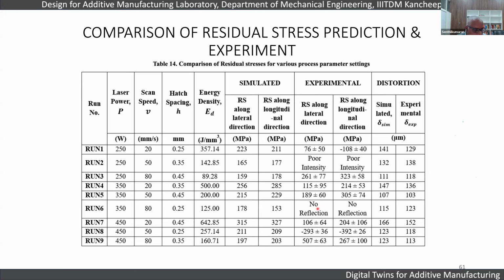So as I said, 3D printing is always very difficult to measure distortions and also correlate with the simulation. We have done this with several software tools, not just one. We used several commercial tools which can give us distortion and residual stress predictions. And we found that many of the softwares fail to give us accurate results, partly due to the fact that our measurement method is also not so accurate.